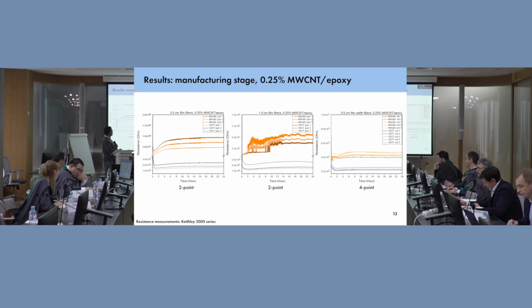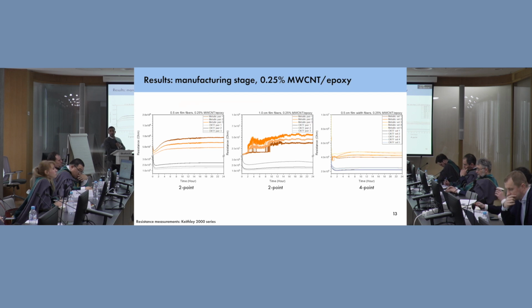We see for our 0.25% by weight multi-wall carbon nanotube nanocomposite that we have a good resistivity range. It's in the range of what we see in literature. For our comparative, which I missed during the presentation, we compared our results to traditional electrode systems which are used. For metals, we used embedded copper wires and silver paste. So in this case, our metallic pairs, because we're using 2-point here and we changed the set for 4-point later, show quite a bit of noise. They show quite a bit of magnitudinal difference as well.